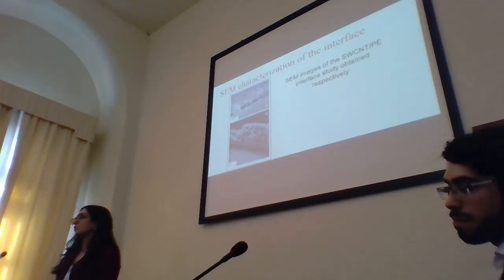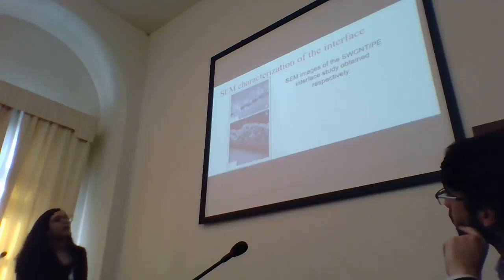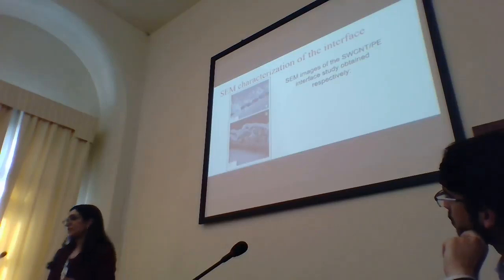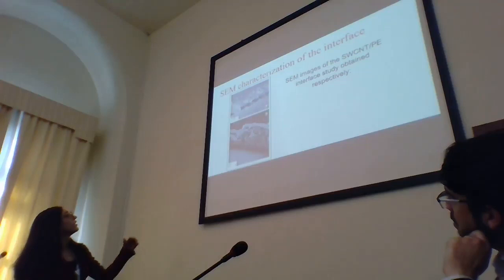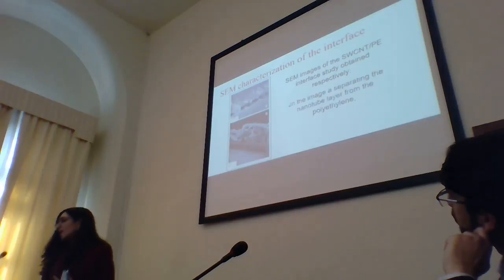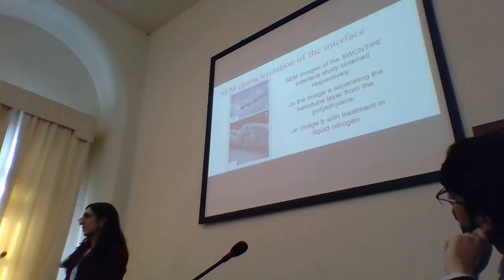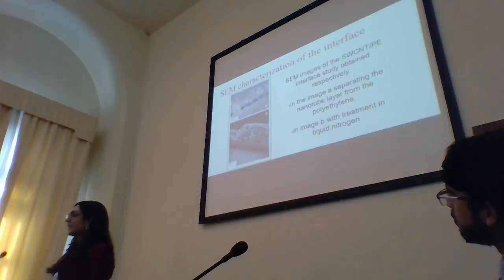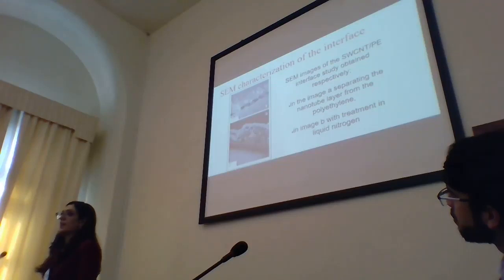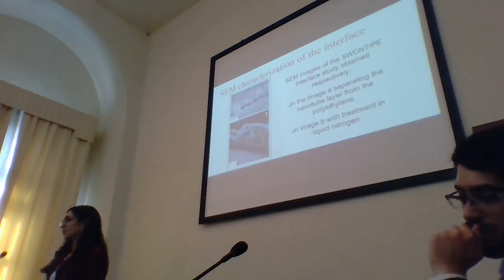We have done SEM characterization of the interface to better understand the mechanism of the anchorage of the single wall carbon nanotubes into the polymer. In this case, we have studied polyethylene. In the first image, image A, we have mechanically separated the upper layer of the carbon nanotubes from the polyethylene, and we can see the roots of the carbon nanotubes that penetrate into the substrate. But as you can see in image B, where the separation of the nanotubes from the substrate is done after a treatment in liquid nitrogen, there is the possibility that also the polymeric chains go up and go around the carbon nanotubes.